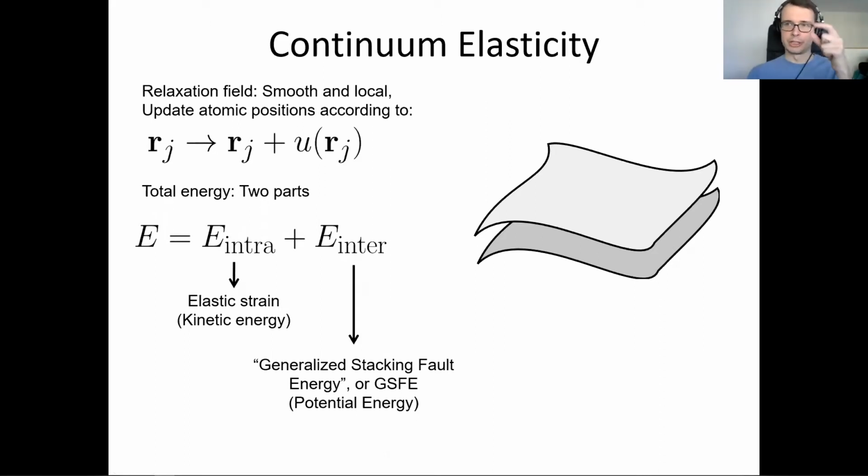So if the 2 layers are aligned with each other, for example, in graphene, this is very unfavorable. But if they're at the AB or BA Bernal stacking, this is much more favorable. However, changing the stacking in a Moiré pattern causes some light strain in the system. Areas shrink, other areas expand. And so there's going to be a competition between these 2 terms.